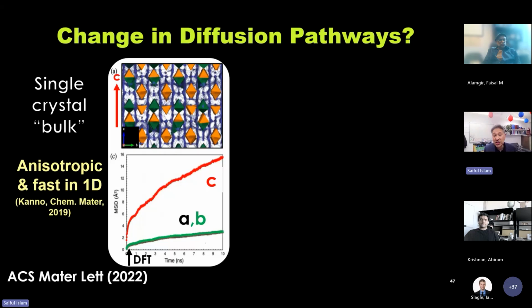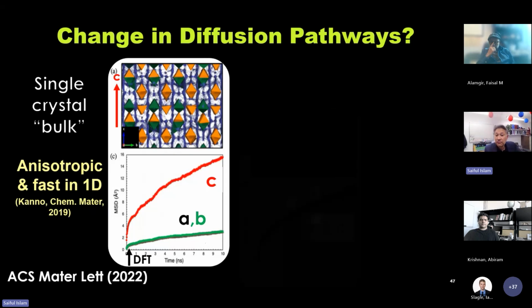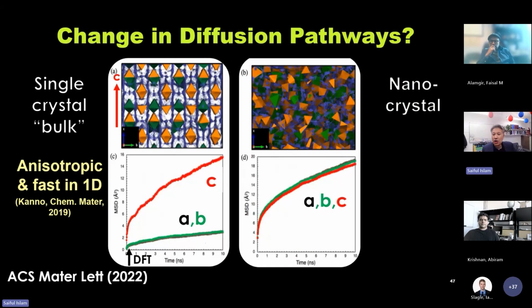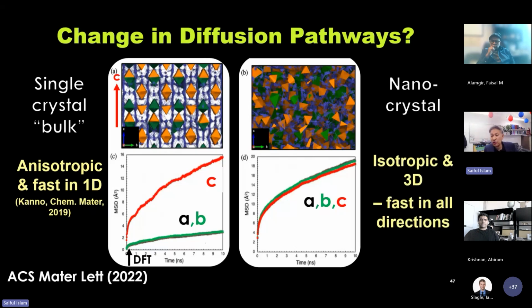This was not new. I'm not saying this is new. This has been found before, for example, by Kanno a few years ago. What's new is what's on the right. On the nanocrystalline, you can see straight away the structure is much, much more disordered, confirmed by the RDF. And the lithiums are moving in all directions, again confirmed by the mean square displacements. A, B, and C are completely identical in all directions, i.e. isotropic lithium-ion diffusion, 3D, fast in all directions.